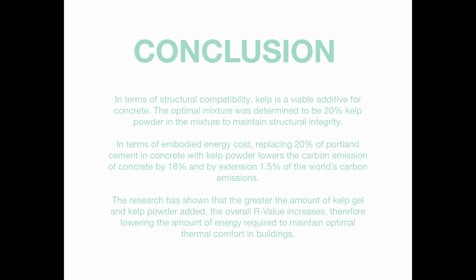So to wrap things up, in terms of structural compatibility, kelp is a viable additive for concrete. The optimal mixture was determined to be 20% kelp powder in the mixture to maintain structural integrity. In terms of embodied energy cost, replacing 20% of Portland cement in concrete with kelp powder lowers the carbon emissions of concrete by 18%, and by extension 1.5% of the world's carbon emissions.